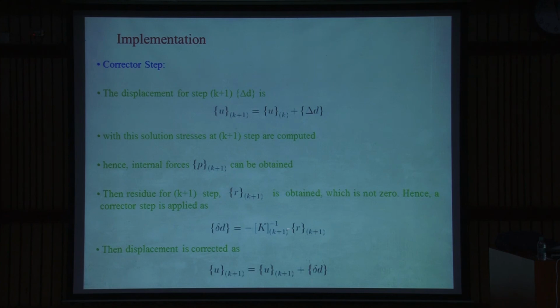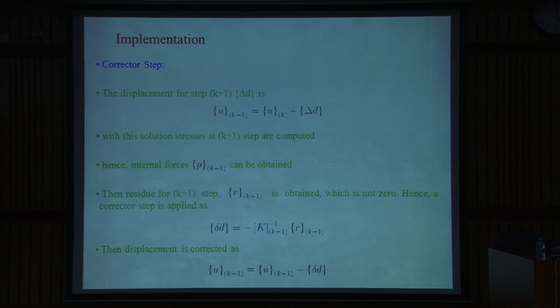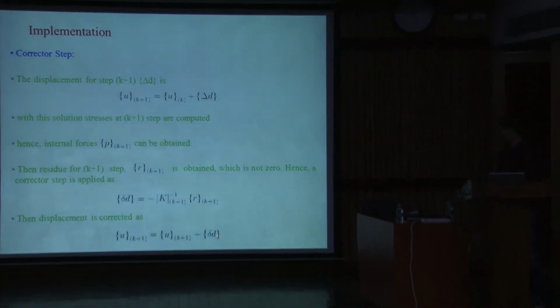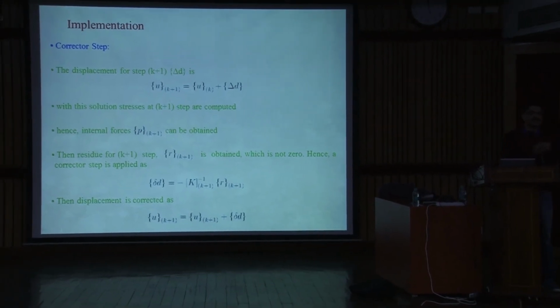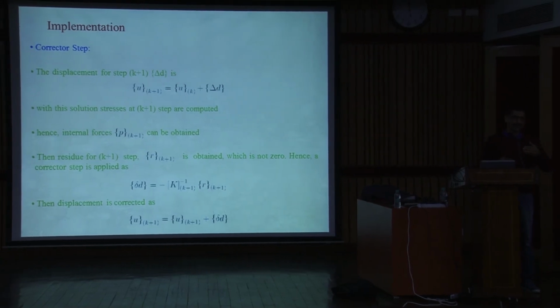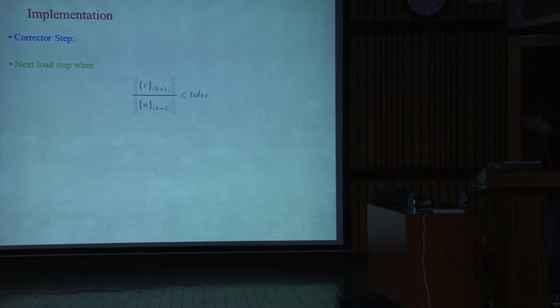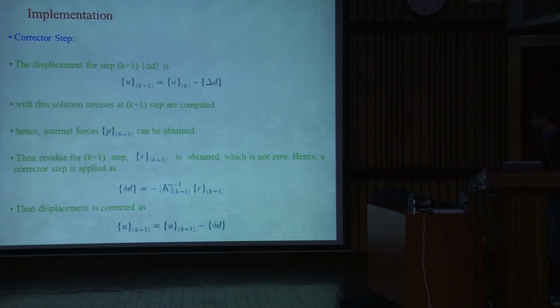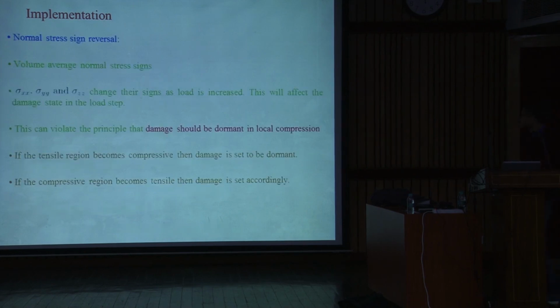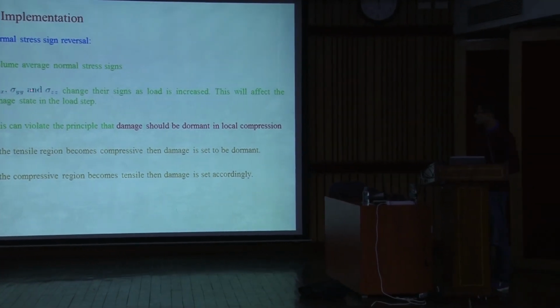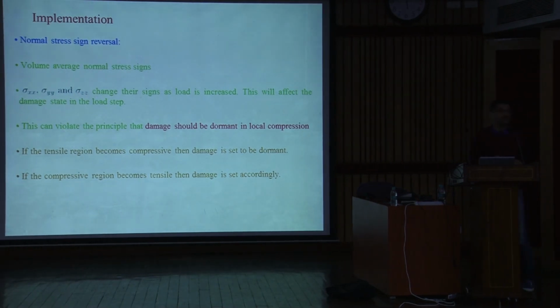In this entire process, you have to assure that the damage indicator you started with at the beginning of the step and what you have at the end of the step should be the same. Then once you get this, you will stop when you reach the tolerance. As I said, whatever damage indicator you started with in that particular step should be the same in the corrector, because the normal stresses sigma xx, yy and zz may undergo reversal of signs, that is compression will become tensile, tensile may become compression, and so on.